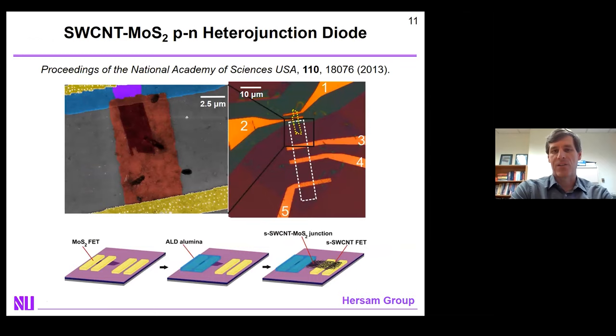that historical precedence. What we were doing at the time was making heterojunction diodes between N-type molybdenum disulfide and P-type single-walled carbon nanotubes. In the initial device, we had a lateral overlapped P-N junction from the nanotubes and the MoS2. And on the back of this device, we would have a dielectric and then an underlying gate. So we could then gate this P-N heterojunction diode.